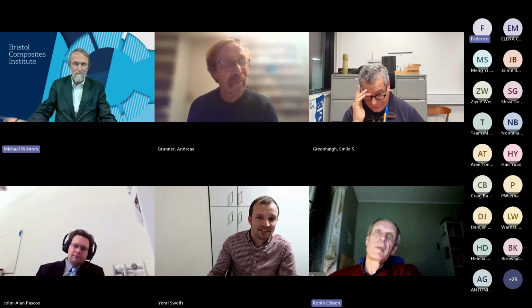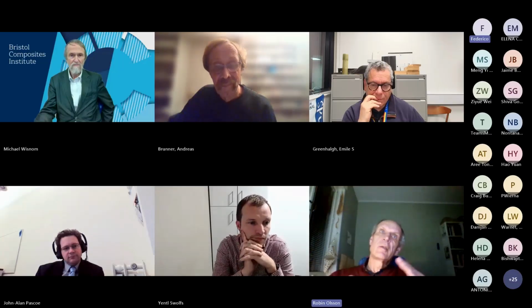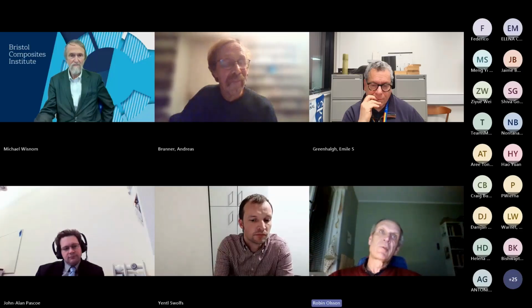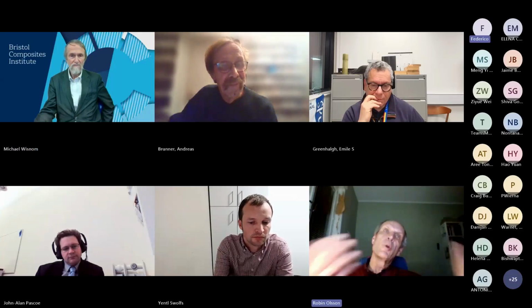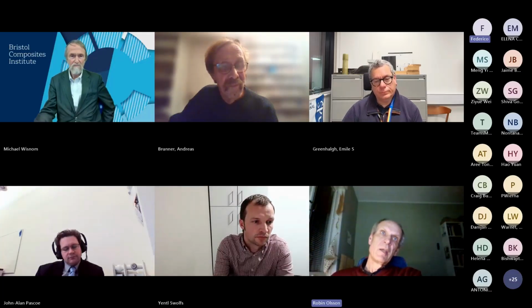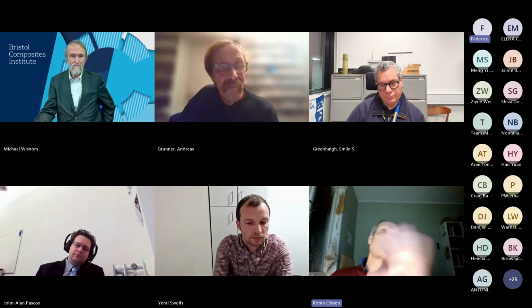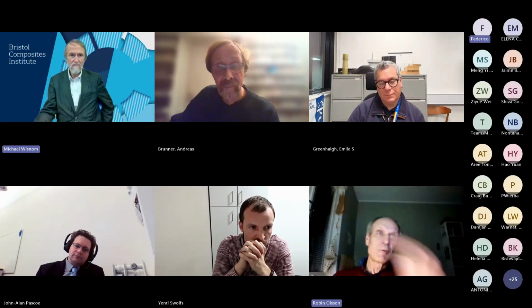One important piece of work was by Suo and Hutchinson many years ago. They demonstrated how shear hackles, these sigmoidal cracks, can be linked to mode 2 toughness and G1C. They established a very good relation, which agrees with most experiments. Of course there are some deviations, but basically G2C is about 3.1 times G1C. That applies as long as you get the sigmoidal cracks and shear hackles, which applies for brittle and semi-brittle materials. Emil had a PhD student looking at this for sandwich panels, for example.